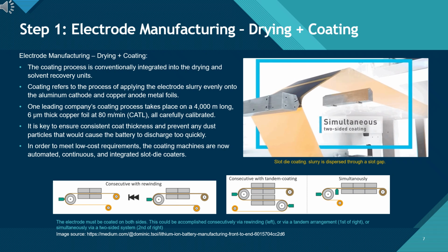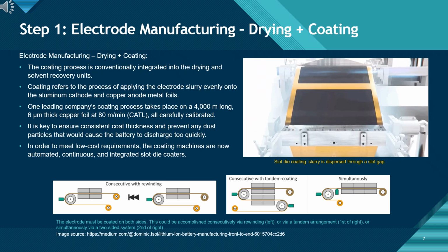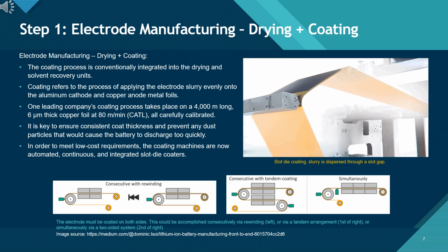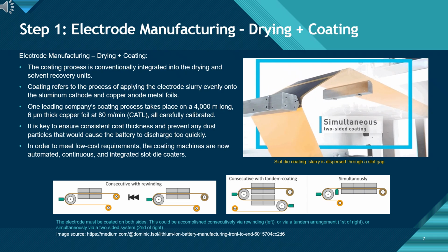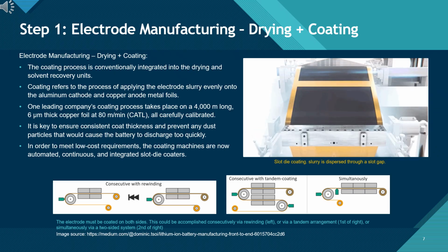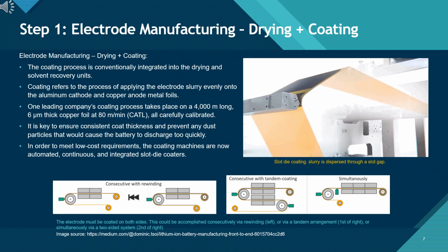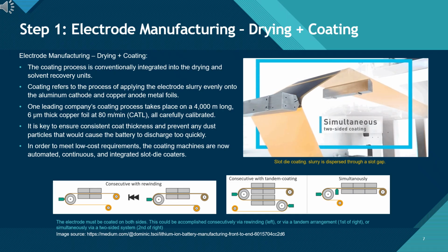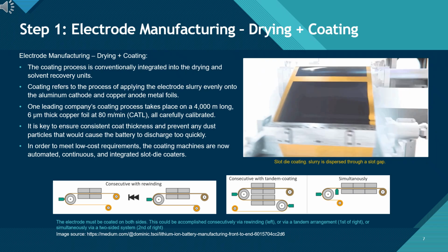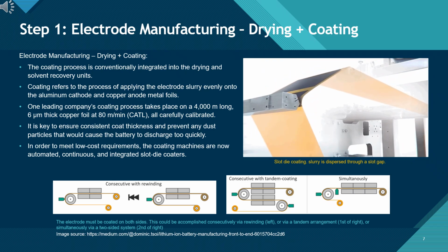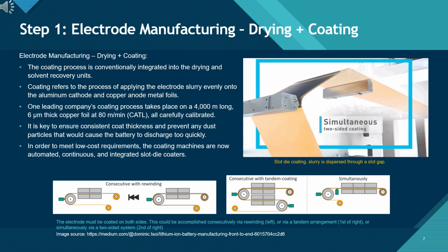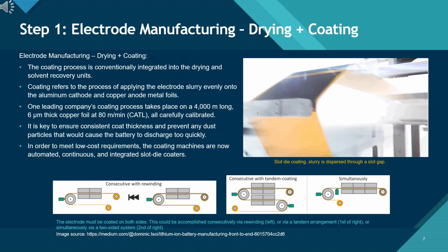As the foil passes through the line, it is dried immediately, and the solvent is recovered. The foil must be coated on both sides, which can be achieved by rewinding the roll, using a tandem coater, or a simultaneous two-sided system, as shown in the diagrams. The key here is consistency. Every micron of coating thickness matters. If the layer is uneven or if dust particles become trapped, the battery may exhibit poor performance or discharge too quickly. That's why these machines are fully automated, continuous, and enclosed so the process stays stable and contamination-free.